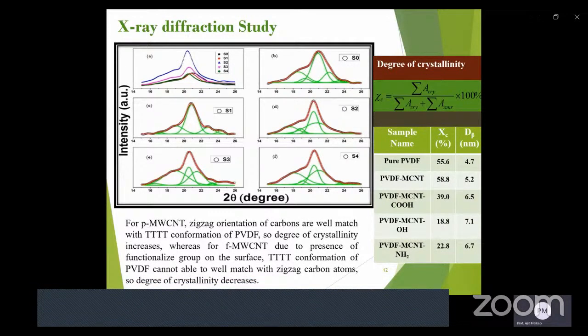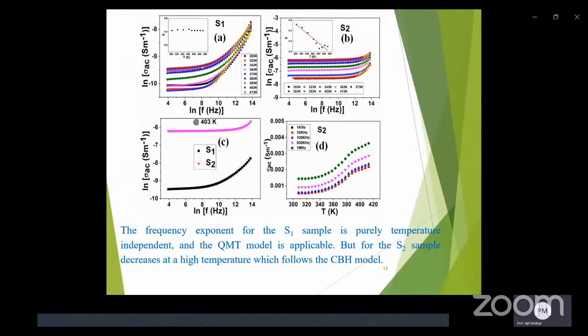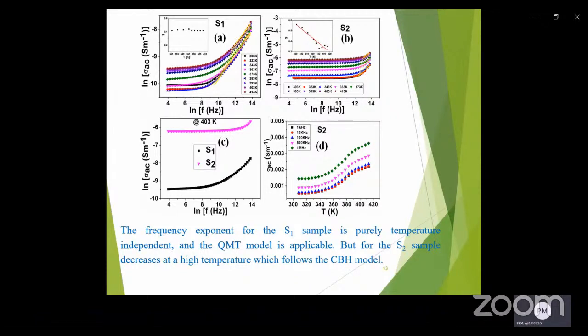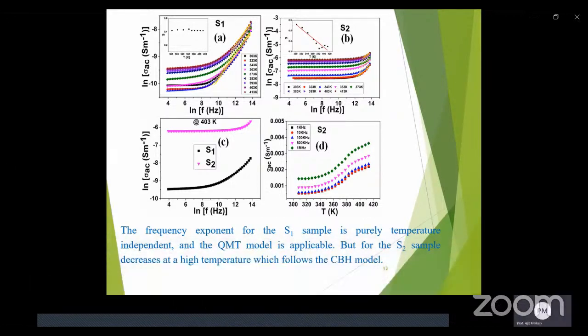The frequency variation of AC conductivity with temperature has been shown here. The frequency exponent s can be calculated from the slope of the straight line part of the curve. The frequency exponent for S1 sample is purely temperature independent and follows the quantum mechanical tunneling model, whereas for S2 sample it decreases, which follows the correlated barrier hopping model.